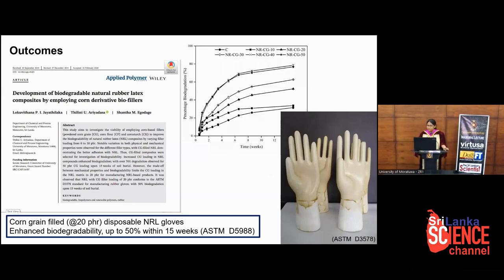We were able to produce disposable gloves by incorporating 20 phr corn grain starch, and this test is conducted to find the biodegradability in soil burial in aerobic conditions, and only 50% of the biodegradability is obtained within 15 weeks. But if you increase the corn grain loading, we can achieve even 80% biodegradability within 15 weeks. However, it gives poor properties and we cannot use it for processing of latex products.